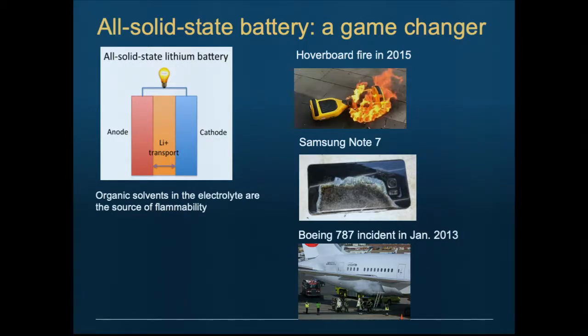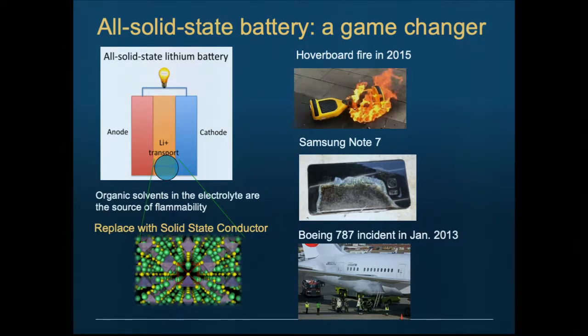In an internal short, the battery releases its energy very rapidly. The cathode is highly oxidized. It oxidizes the electrolyte, right? Because the electrolyte is an organic solvent, and you have an explosion or fire internally. The last one was essentially the Note 7 incident. But there have been other ones, right? Lithium-based batteries in hoverboards. Like I said, the Boeing 787 incident, which grounded the whole fleet.